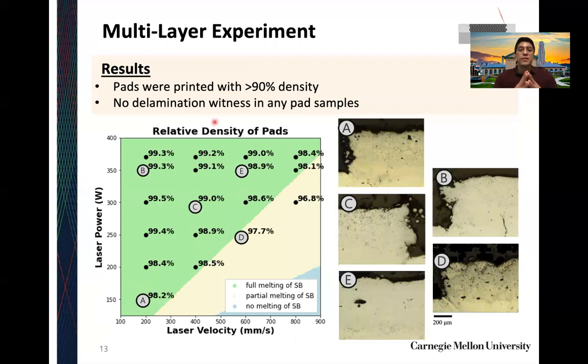And just to quickly go over some of our results, I won't show pictures of every single pad for the sake of time, but here you see 5 different pads throughout the process region. And for the most part, porosity was pretty decent actually, below 3% in all of these. I mean, there's 3.2% here, but we get really highly dense samples. Now, porosity here was measured using an image analysis technique, so it's almost like a 2D projected porosity. But one thing we did notice about all of our pads was the lack of delamination, which is really good in the sense that we don't see early heat buildup, which is what essentially induces the thermal warping that delaminates the pads.